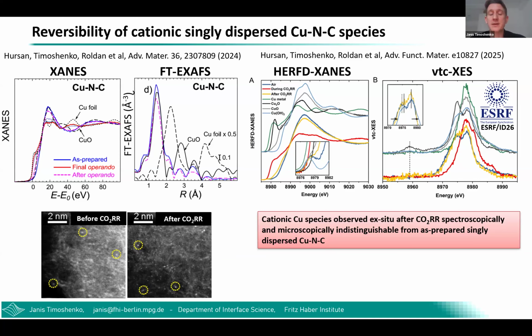So in this regard, this system is actually a very nice example of why it's important to do these operando and in situ studies, just because, as you can see in this case, just by looking at the catalyst after reaction, you can get a completely misleading picture about what's actually happening with it under reaction conditions. And of course, the process itself is very surprising. We can probably understand why these single sites tend to cluster into metallic particles. However, it's harder to understand how these metallic particles can be pulled apart and form back again these singly dispersed sites.